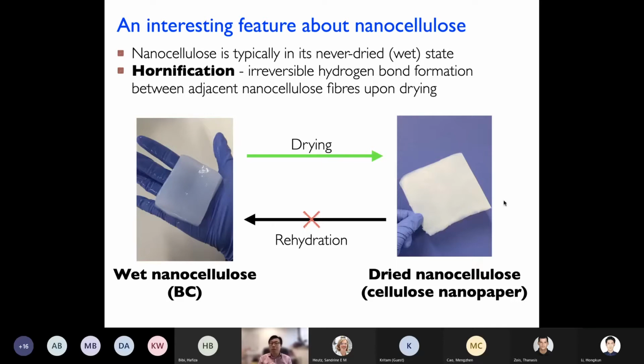The reason is that when these nanocelluloses are at such a small length scale, 50 nanometers, 15 nanometers, or potentially even 3 nanometers, depending on the degree of refinement you have put the cellulose through, the surface area between the nanofibers is huge. So as you dry them, so much hydrogen bonding forms between the nanofibers that even if you dump it back into water, it just won't rehydrate anymore, because of the hydrogen bonding formed between the individual nanocellulose fibers.